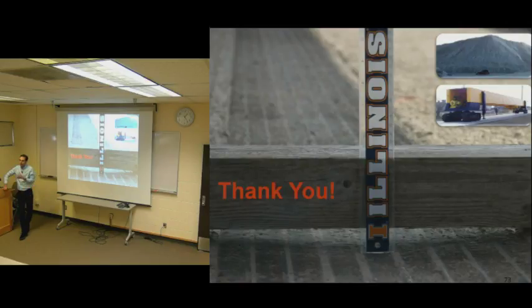You're not going to have oven dry. Exactly. So when we did it in the lab, the moisture content that was targeted is the actual moisture content that we had when we collected the samples from the quarries. But before the construction, we had some rain, so those stockpiles were wet. What we did is we spread them out in the big backyard, just to try to dry them as much as possible. But then when we calculated the moisture content after or within the construction, it was still higher than what we tested in the lab.